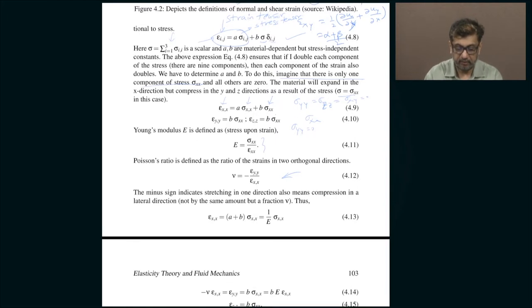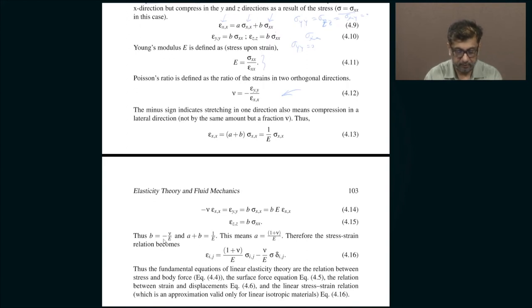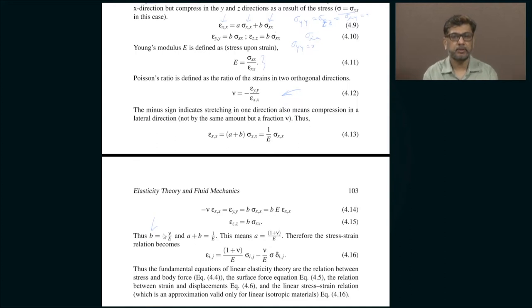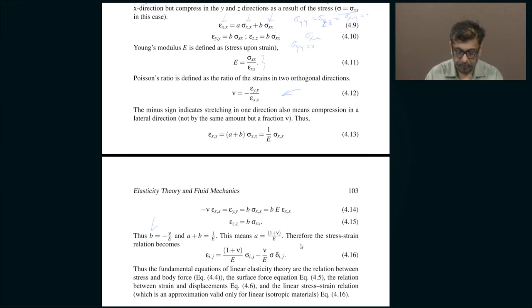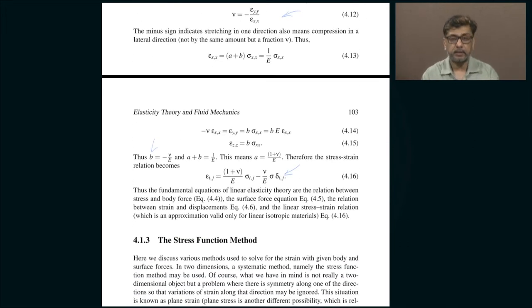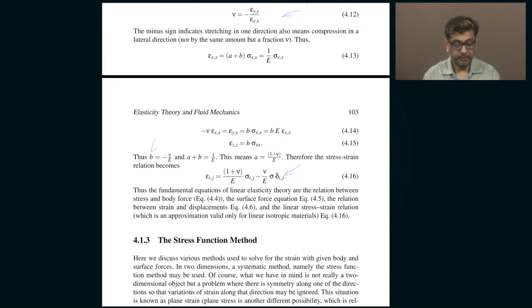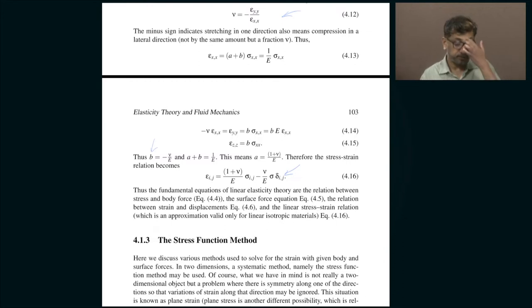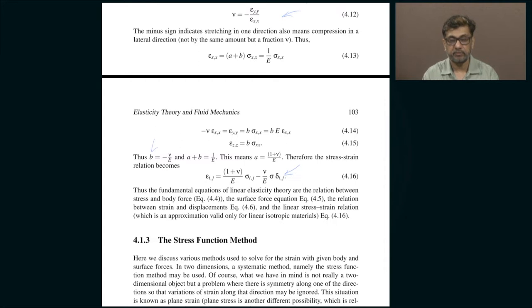It is straightforward to relate a and b to these physical quantities. B comes out as minus the Poisson ratio divided by Young's modulus, and A equals one plus Poisson ratio divided by Young's modulus. Substituting these gives the important relation between stress and strain in a material: for a linear elastic material with applied stress sigma ij, the strain epsilon ij is described by two parameters - Young's modulus tells you how the size changes, and Poisson's ratio tells you how the shape changes.